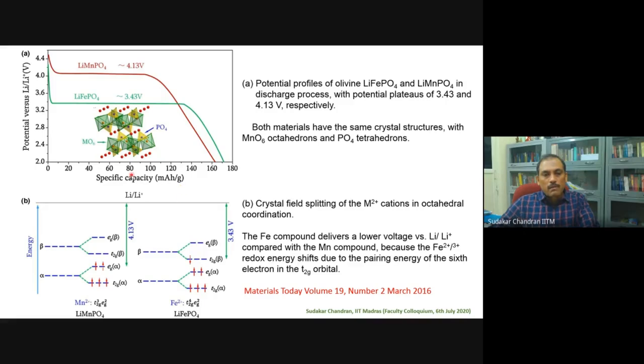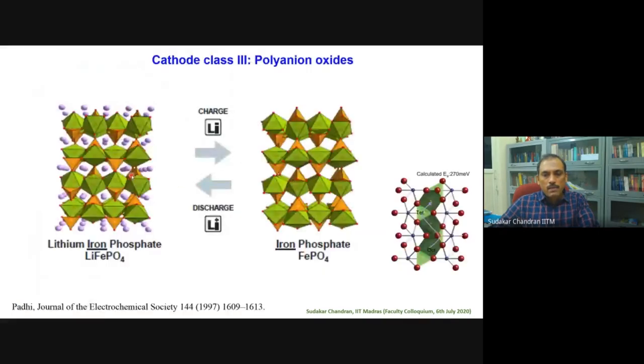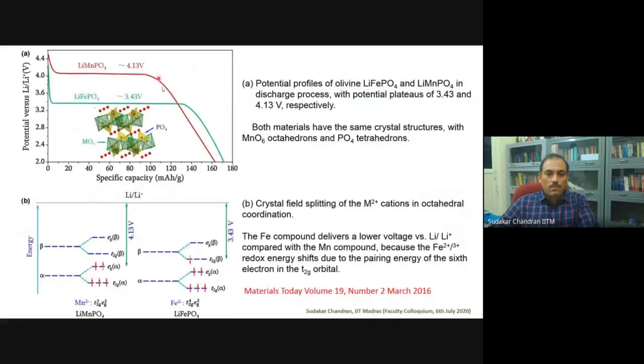By playing with the electronegativity of the anion, one can change the voltage, as was shown in these polyanionic compounds. Of course, there was some confusion here. Iron, being more electronegative, exhibits much less voltage compared to manganese, because as you go from the left side to the right side in the transition metal row, iron would be more electronegative.